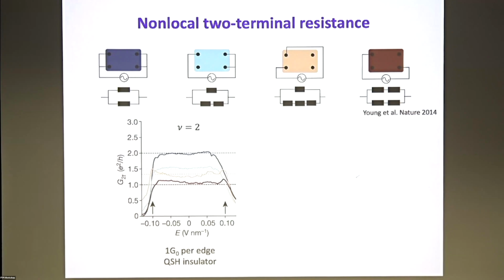So let me just, long story short, this is filling factor 2, the quantum spin Hall insulator, two-terminal conductance versus the electric field. And once you go beyond the critical electric field, the system transitions into a topologically trivial state. So you don't need to look at that; you just look at the small electric field region. Each dashed line with a particular color is the expected value if your edge carries exactly one conductance quantum. For instance, this contribution will give you 2e²/h. This will effectively measure one edge conductance as 1e²/h. So this measurement confirmed that this is indeed a quantum spin Hall insulator with one conductance quantum per edge.